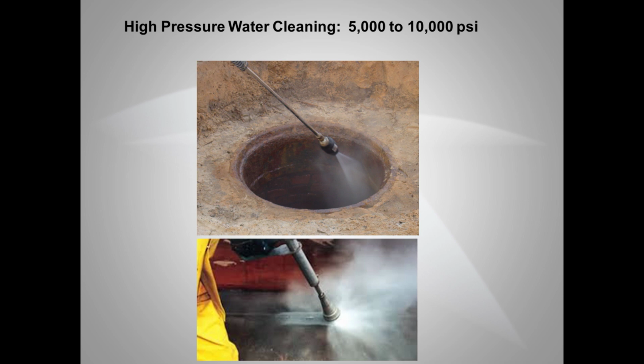SSPC and NACE have now combined, but they had a joint standard, SSPC-13/NACE 6, which called for various methods of preparing surfaces. One of them is what was called high pressure water cleaning, and that's defined by the standards as being between 5,000 and 10,000 psi. Our contractors typically do this at the lower end of that scale, about 5,000 psi. The picture on the top is a 0 degree tip that's rotating, and at 5,000 psi it's pretty strong. The picture below that is ultra high pressure water blasting, and those pressures above 10,000 psi are just not really suitable for use inside a manhole.